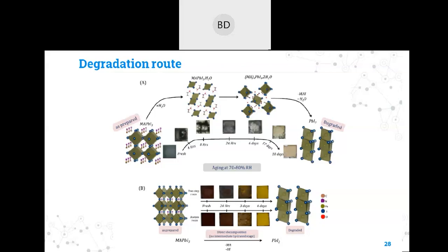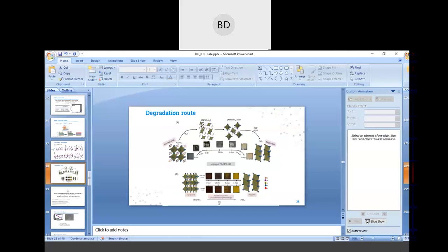It's like when you have the water molecule intact in your film. First thing is there will be very little perovskite available. Second is it has already formed a double hydrate. So this phase is not at all a photoactive phase. This has no photoactivity in terms of governing the solar cell performance. So first, absorption is very low. Second, this doesn't contribute in photoactivity. So it will be detrimental to the performance within a few hours. I hope I am clear.